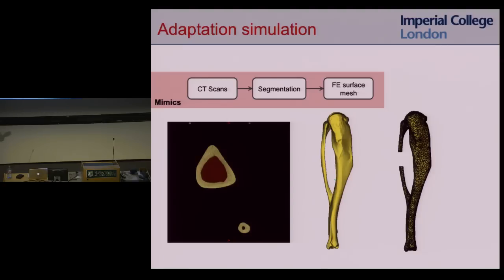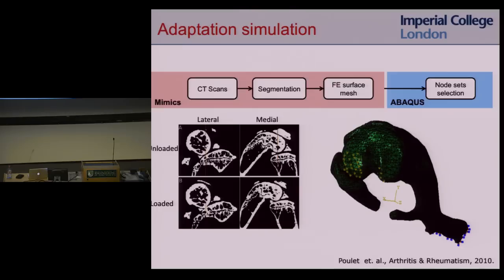So we start with our CT scans of the bone. We can create a finite element mesh. We then load the bone. We get our loading conditions by, we actually loaded a bone and scanned it at the same time so we can see how the bones move relative to each other. So we get the rigid body motion, and that gives us an indication of the loading on the bone. We know the magnitude of the load, and now we know relative distribution based on these images.